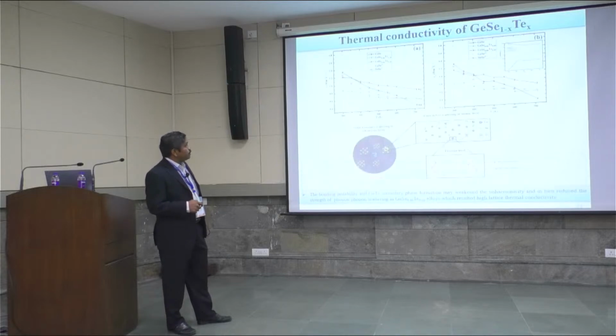And based on the measured resistivity and the Seebeck coefficient, the power factor has been calculated. And the power factor is quite high for the tellurium substituted samples, compared to the pure system. Okay? And then the thermal conductivity of the system has been measured for the tellurium substituted as well as the pure systems. And look at that, compared to the pure system, the tellurium substituted system shows relatively low thermal conductivity, especially for the 10% substituted one. But it slightly increases when the tellurium content is more.